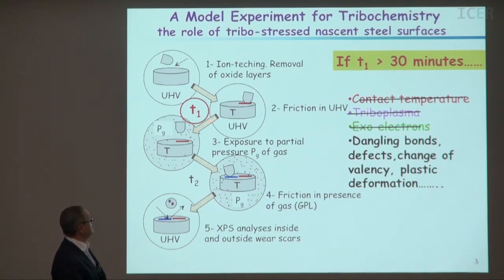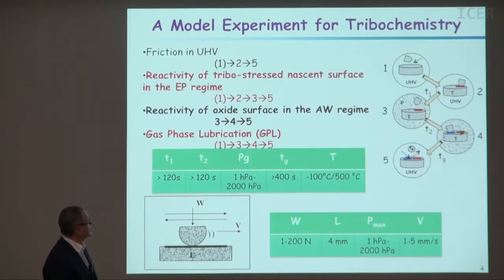If this time is sufficiently long, for example after 30 minutes, the temperature, triboplasma and exoelectrons cannot be produced. So we have only the surface activity here, and we can manage the reaction of the gas with the surface. This is the strategy. With this strategy, we can study several things. First of all, the reactivity of the nascent surface with the gas, by using this sequence here directly, 1, 2, 3, 4, 5. We can also study gas phase lubrication, so the lubrication in presence of the gas.